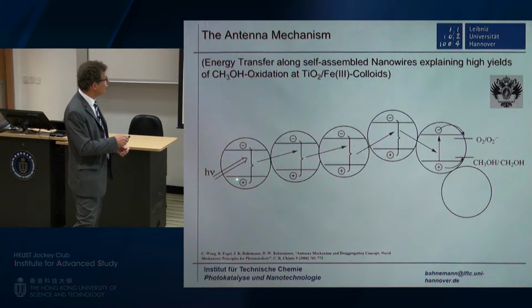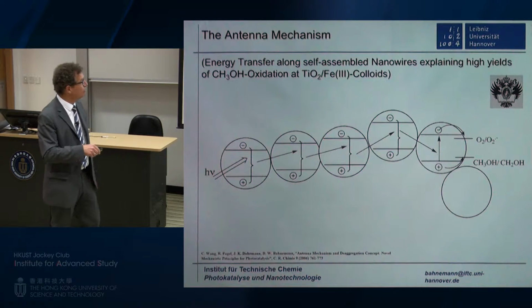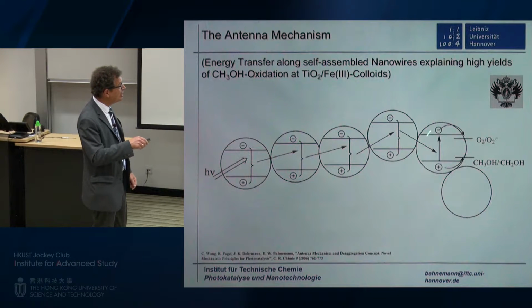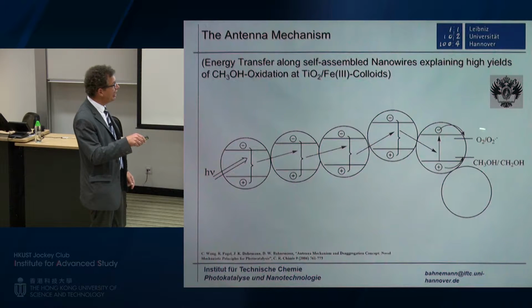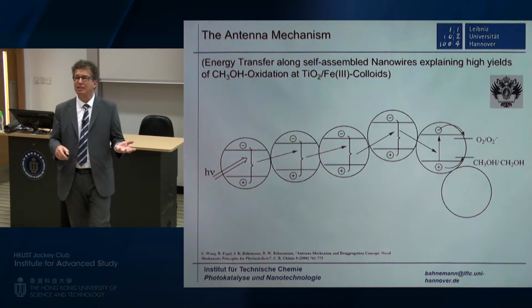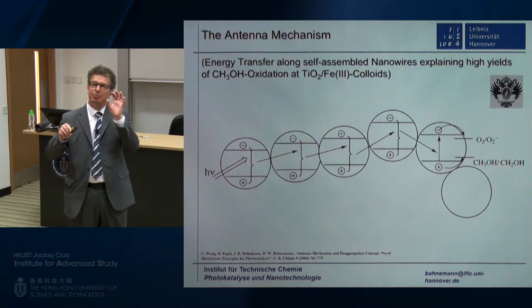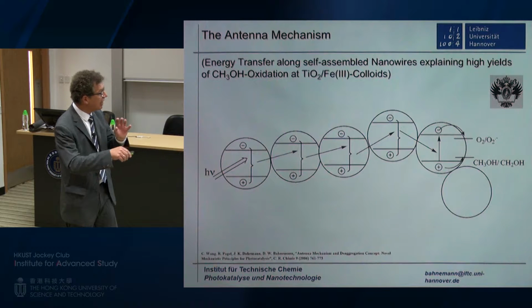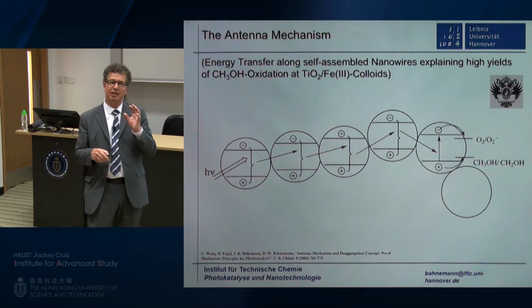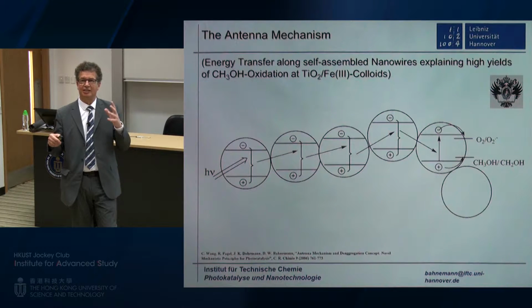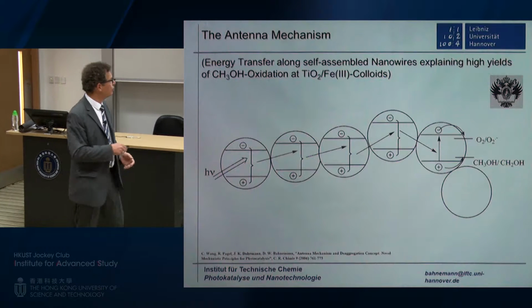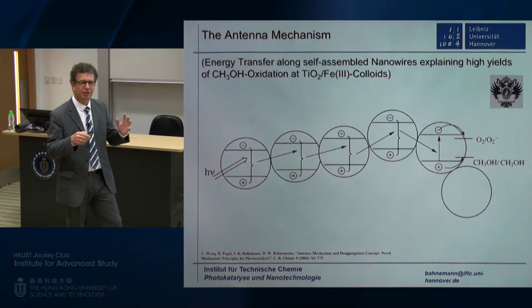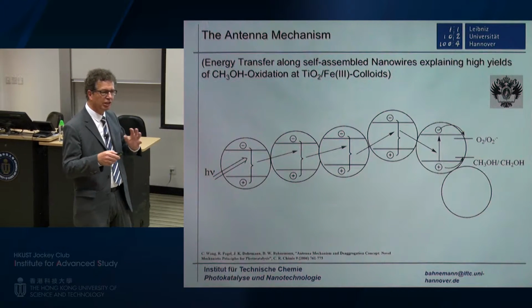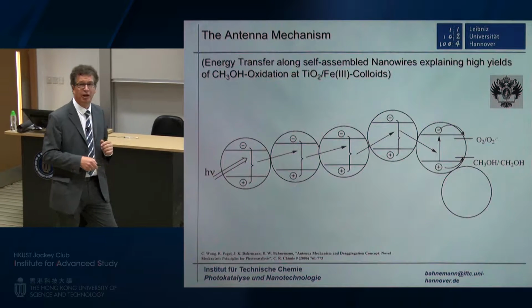because we have some indication that these nanowires can act as antenna systems. So you absorb your photon in one of these particles, then this energy as an exciton energy can move along this nanowire until it finally finds a particle where you do have the adsorbed electron acceptor and or electron donor, and then the reaction comes about here. So the place of light absorption and the place of reaction do not necessarily need to be on the same particle, but they can be remote from one another. You should try and imagine this system not as two-dimensional. For sure it's three-dimensional, but this is hard to put on a transparency. I'm sure this is a three-dimensional network of these nanoparticles that we have to deal with.